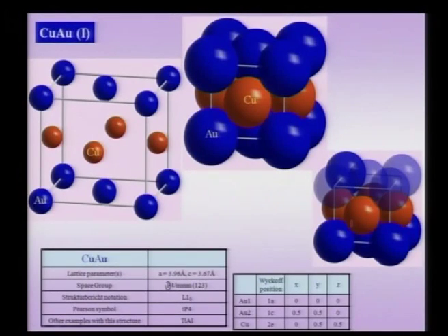So, this is an example of a regular distortion. Suppose I had a disordered structure CuAu1, and then what would happen? It will be a single lattice parameter structure, though it will be a reflection in some sense of the kind of arrangement of the atoms. But now, since it has got ordered, the symmetry has been lowered, and so this has now become a tetragonal structure which is reflected in this T here. So, it is a tetragonal structure, and therefore when this ordering takes place, the c/a ratio will change. So, this is a more regular kind of distortion.